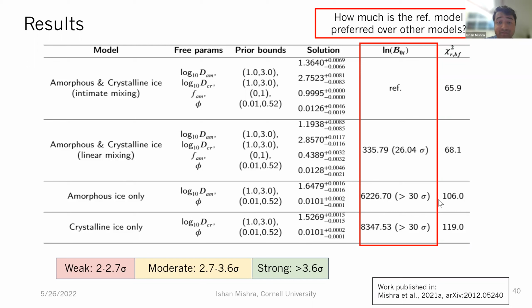For this preferred model, the results that we got for our parameter estimation are shown here. The parameters that we were fitting for were the grain size of the two kinds of water ice, the fraction of one of them, f, because the other one is dependent, 1 minus f, and the porosity. What we got was small grains, around 50 microns, of amorphous ice, very large grains of crystalline ice, a very large amount of amorphous ice, and a very highly porous surface.